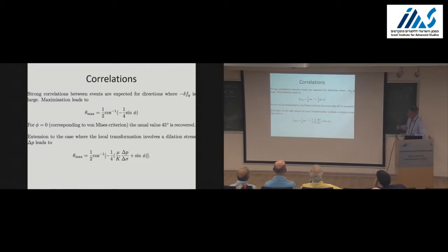So now what we suggest here, and I don't have a proof for that, is that if there are strong correlations in the yield functions, this is where I should observe preferential directions in the correlation picture. So when we have these weakly interacting, kind of isolated events, then I can expect that one event at the origin will preferentially trigger a new event where the change in the yield function is maximum. Okay, this seems a reasonable assumption,